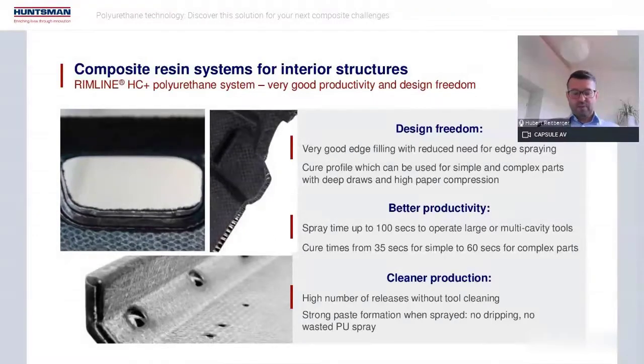The resin provides a better productivity with its 100-second spray time to operate large or multi-cavity tools, while keeping cure times short at 35 seconds for simple or 60 seconds for complex parts. A high number of releases without tool cleaning is possible, and the patented strong paste formation when sprayed results in a cleaner production as the resin is drip-free.